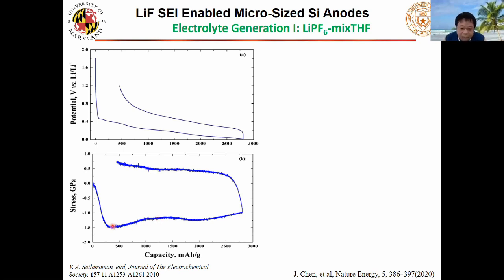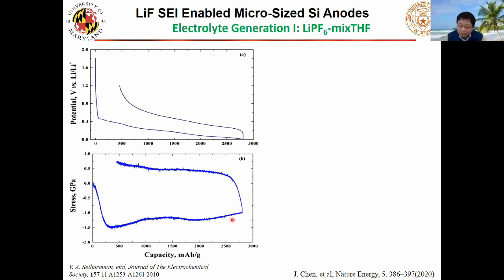If the electrolyte is not penetrating, traditionally this plastic flow does not happen because when they crack, electrolyte penetrates inside and they cannot flow. But in our case, if we have a shell that completely avoids electrolyte penetration, we will see this flow. We have lithium PF6 with a reduction potential at 1.2 V and THF at 0.3 V. When the potential decreases during lithiation, the open circuit gradually decreases below 1.2 V — PF6 reduces first, forming lithium fluoride. Because this initial lithiation is small, the volume change is very small. They continue to grow the SEI. At a later stage, when you continue lithiation, the stress increases and then crack occurs for micro size — you cannot block this. But at this potential, only PF6 reduces, not THF. So the lithium fluoride holds it, and because the bonding is so weak, even when cracked, the SEI remains stable.